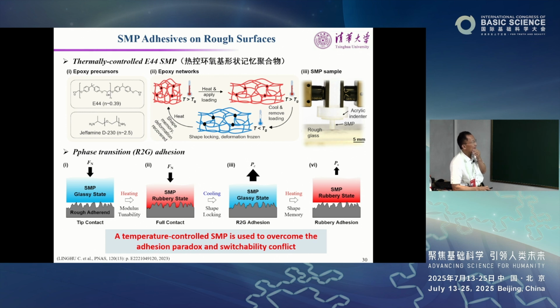Okay, so for example, we take this so-called E44 shape memory polymer. Okay, very simple chemical formula. It's essentially a polymer network. Above Tg, you can heat it, right? To do some deformation, you can stretch it. Then you cool it down, so that deformed shape will remain. Okay, then you heat it up above Tg, and it will recover its original shape. This is the deformation, shape locking and memory, shape release.